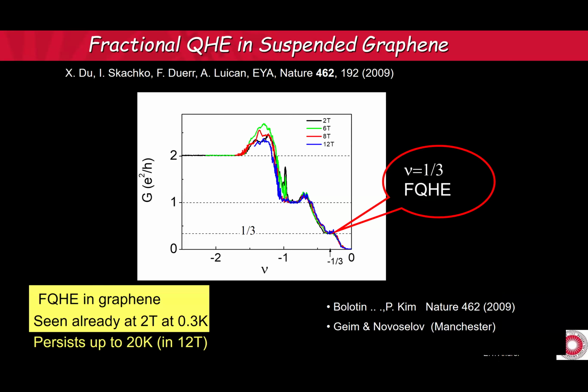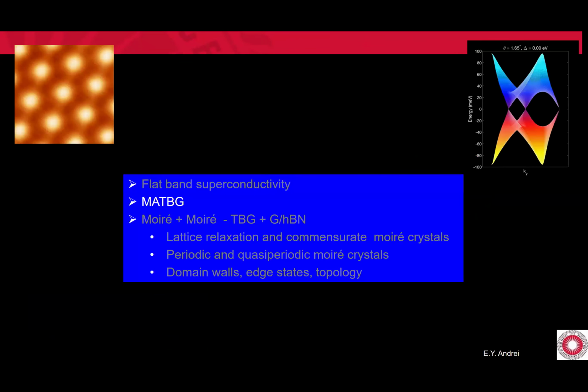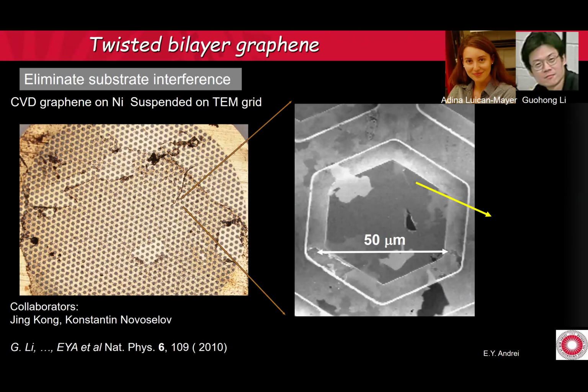So first of all, people didn't believe in correlations in graphene at all. So this actually proved that this is not a trivial uncorrelated system. Not only that, but it is much stronger than in gallium arsenide. We already see it at 2 Tesla at 300 millikelvin. We don't have to go to the magnet lab to see the fractional quantum Hall effect. Very strong interactions.